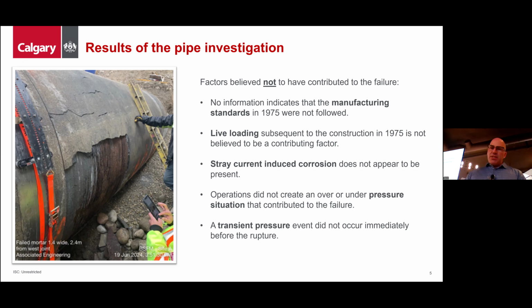We also found that live loading subsequent to the construction in 1975 was not believed to be a contributing factor, and stray current induced corrosion does not appear to be present in the vicinity of the pipe break. Interestingly, we did need to rule out the fact that pump operations from our plant were part of the failure, and we identified through transient analysis that both the pumps at the Bearspaw water treatment plant as well as the secondary pump stations did not create an under or overpressure situation that contributed to the failure. And as I said, a transient pressure event did not occur immediately before the rupture.